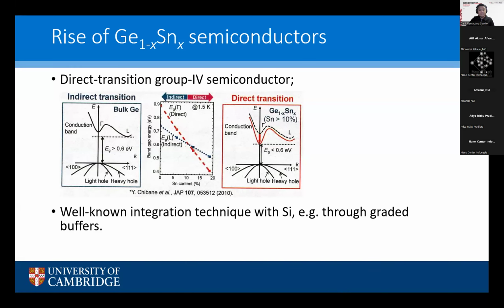So as you may know, bulk germanium is an indirect band gap material with the L value lower than the Gamma value. And the beauty of incorporating tin to create a germanium tin alloy is that you can tune these Gamma and L values in such a way that for tin content larger than 10%, you will have a direct band gap material.